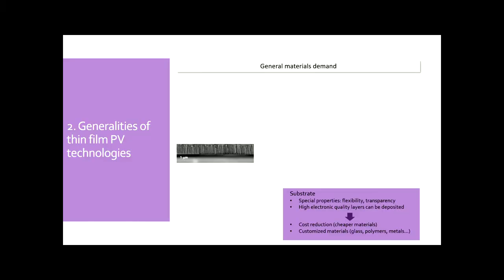In particular, the good thing about these technologies is that the substrate can have special properties like transparency and flexibility, that are not so common for silicon. And also, of course, one of the requirements is that high electronic quality layers can be deposited on this substrate. That has to be compatible with high electronic quality layers. But this allows for cost reduction, because we are using cheap material, we are substituting 300 microns of silicon for 3 millimeters of glass. And of course, glass is much, much, much cheaper than silicon. So our substrate right now is really a cheap material.